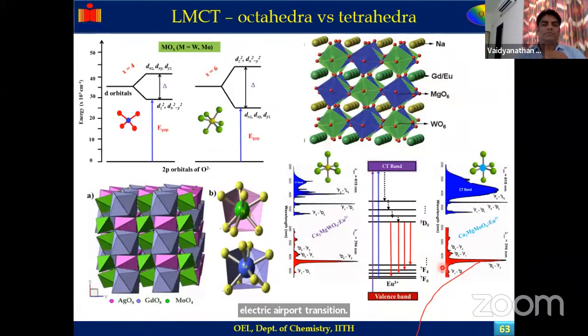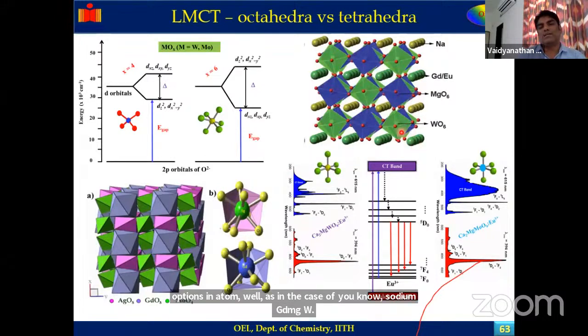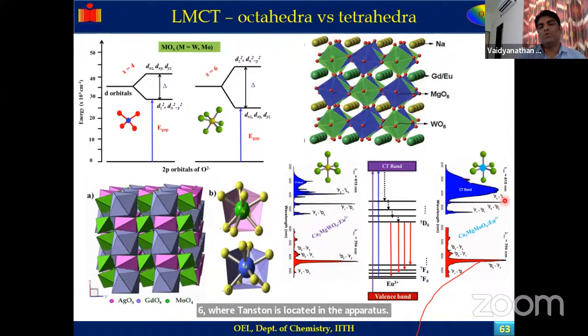Of course, I have told you already, with the example I'm telling here, AgGdMoO4, where molybdenum is surrounded by four oxygen atoms, whereas in the case of sodium GdMgWO6, tungsten is located in the octahedral site. The octahedral site has good absorption, this blue color you can see, but the tetrahedral has poor absorption. So this is the difference between the scheelite structure, with tungstate or molybdate in 4 coordination, whereas in the perovskite structure we have a 6 coordinated site. So that can be used to get a light here.